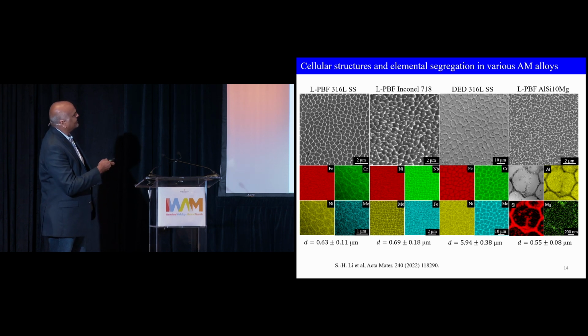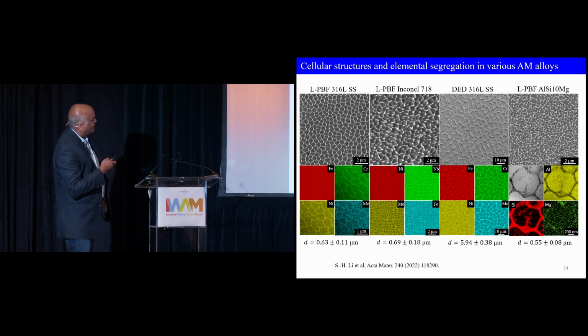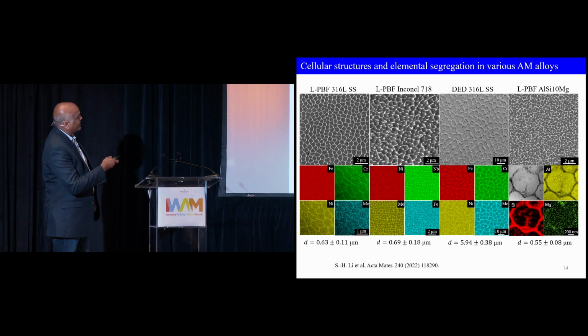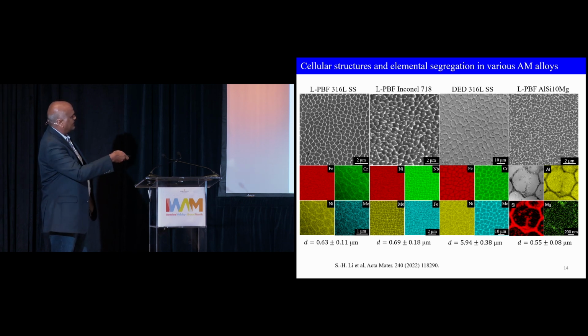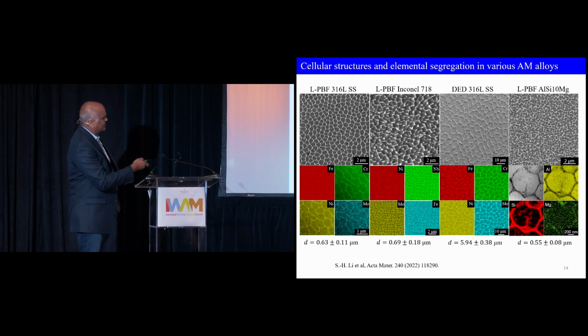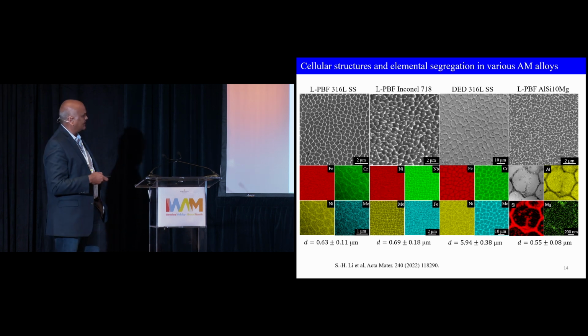The length scales depend on the technique - if you do laser powder bed fusion, the length scales of these cell structures are about sub-micron in scale, 0.6 to 3 microns, etc. But if you take the same austenitic stainless steel, a very common, widely used stainless steel, and use a different manufacturing technique called directed energy deposition, you get a much larger cellular structure, now about 6 microns. So there is an order of magnitude increase in the cellular size.